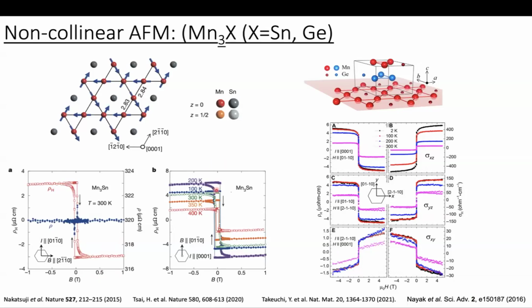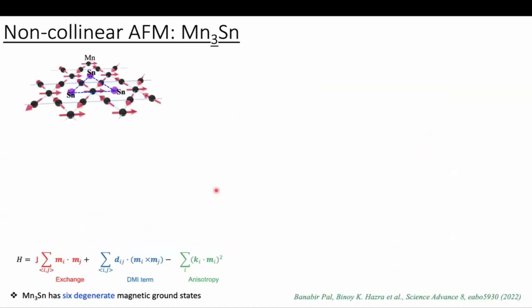Since this compound shows a large anomalous Hall effect, the open question at that time was whether it's possible to manipulate the magnetization or domain structure or not. So with this motivation, we started the work. We have taken manganese-3 tin as a model system. This is a typical spin texture you can see. Here, manganese-3 tin basically crystallizes in a hexagonal crystal structure, and manganese spins form the triangular lattice. The Heisenberg exchange interaction and Dzyaloshinskii-Moriya interaction favor 120-degree antiferromagnetic ordering.